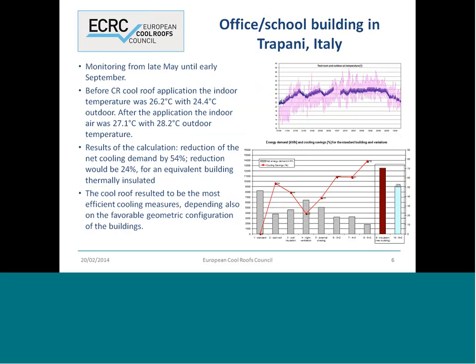The cool roof was applied in the first week of July, as inferred from the blue plot here in this photo, where the measuring of the indoor air temperature in a reference zone was interrupted. Aggregate results of the monitoring phase say that before the cool roof application, the average indoor temperature was 26.2 degrees, with an outdoor average temperature of 24.4 degrees. After the application, the average temperature inside the building was 27.1 degrees, but with an outdoor temperature of 28.2 degrees.